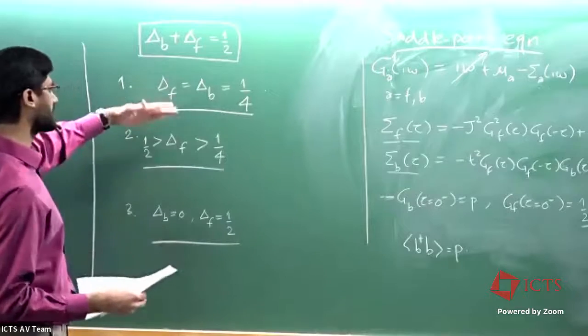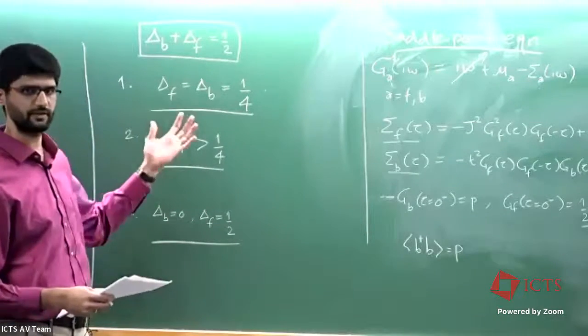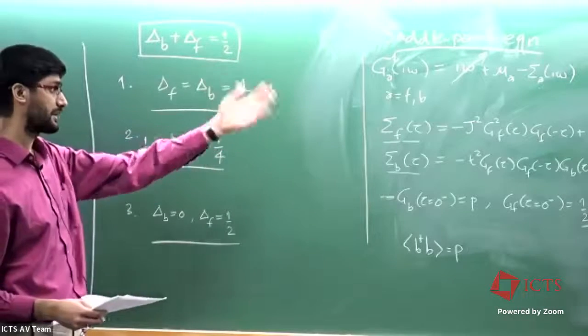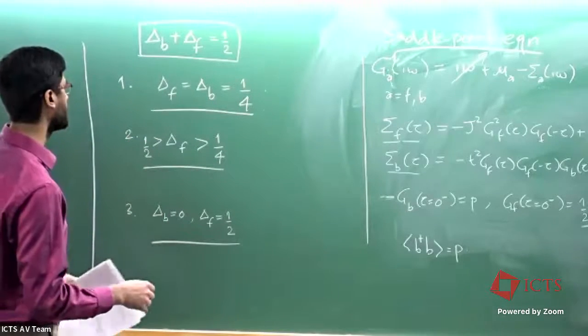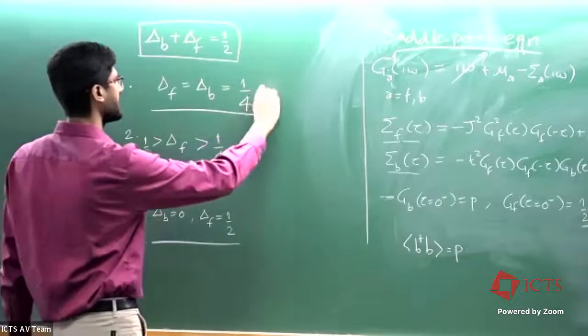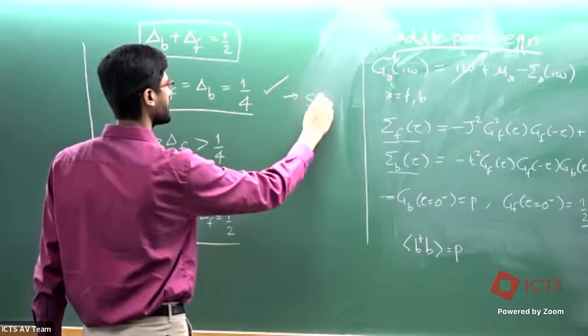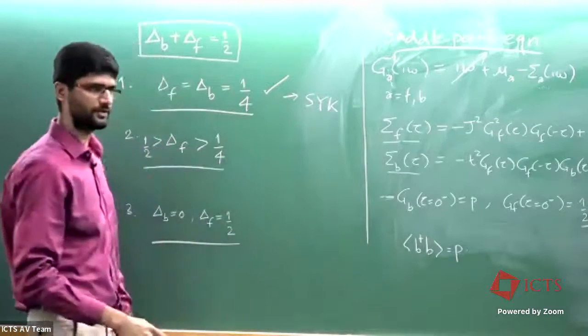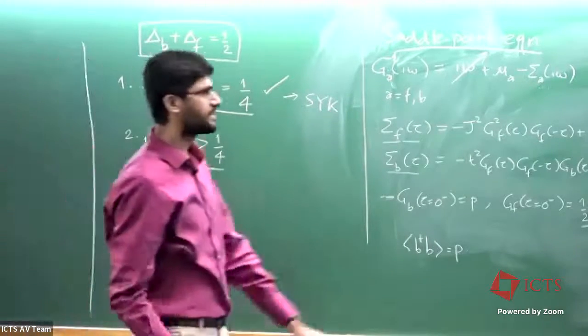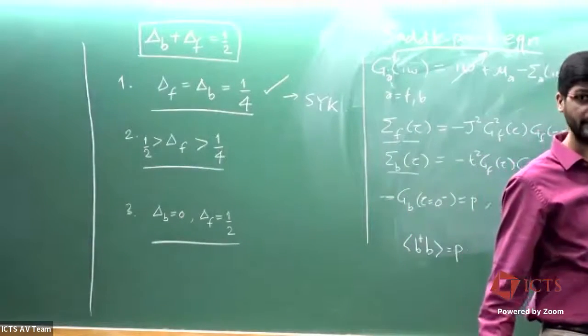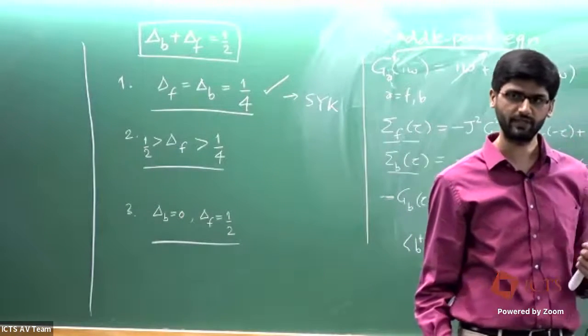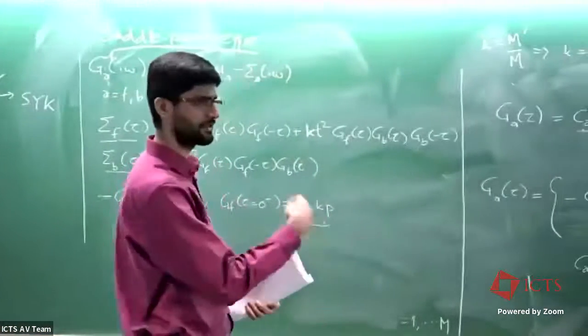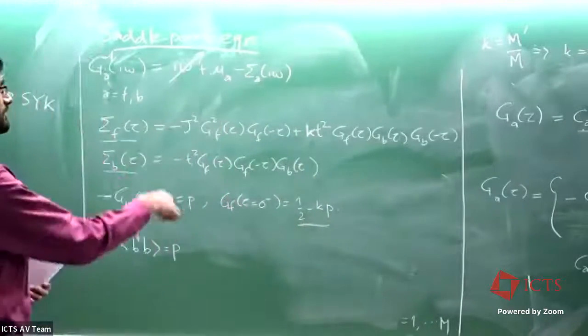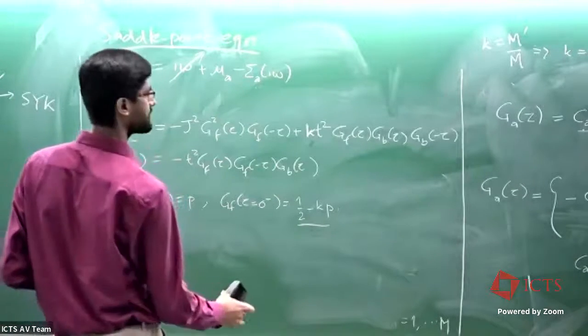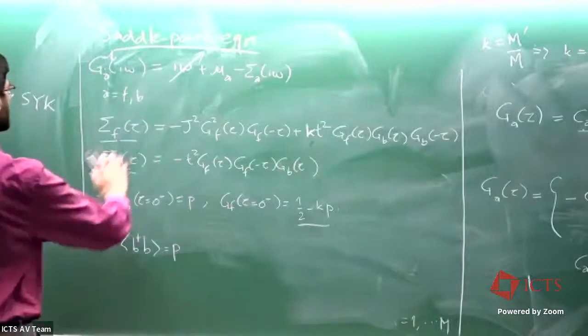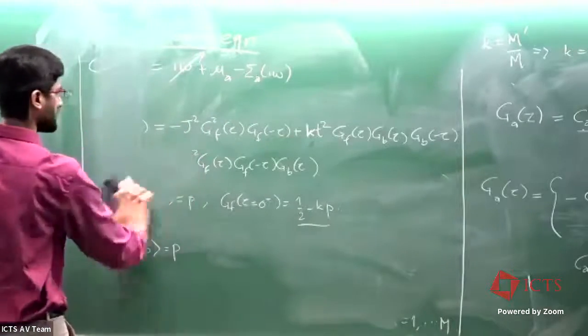So these will describe different critical phases or normal phases of these Schwinger-Dyson saddle point equations for this model. And perhaps you have already noticed that this is the solution that corresponds to your SYK or SYK-like solution. You put delta equals 1/4, the exponent that you get here is square root z. So this is the usual SYK Green's function that you get. To be even more clear, what you can look at is the exponents of your physical observables, which are eta S and eta C. So I think I don't need this anymore.